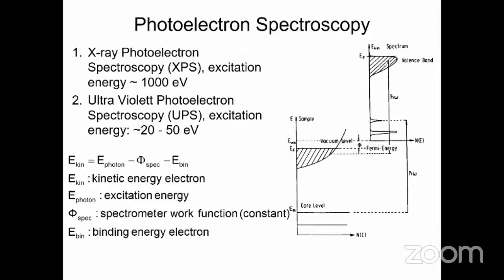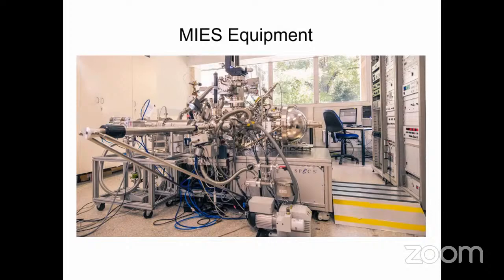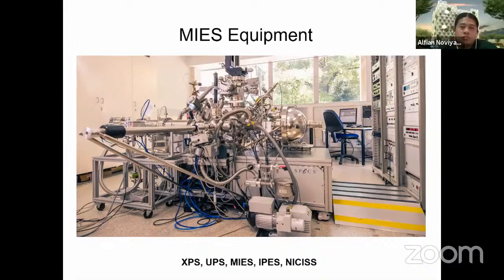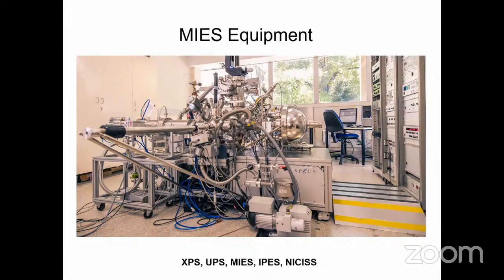We use XPS, and as you know, XPS is used for chemical elemental peaks. It's just a photon ejecting the electrons and recording the binding energy, when the photon overcomes the binding energy of the electron. And this is our machine in Australia. Along with XPS, we also have MIES and UPS. With MIES, we study the outermost layer, which I will not talk about in this presentation for the time being, but this is one of the unique techniques where we use metastable helium to eject electrons from the outermost layer. The depth is just 0 nanometers, just the outermost layer, while XPS can penetrate to about 2 or 3 nanometers, depending on the electron mean free path of the metal itself.